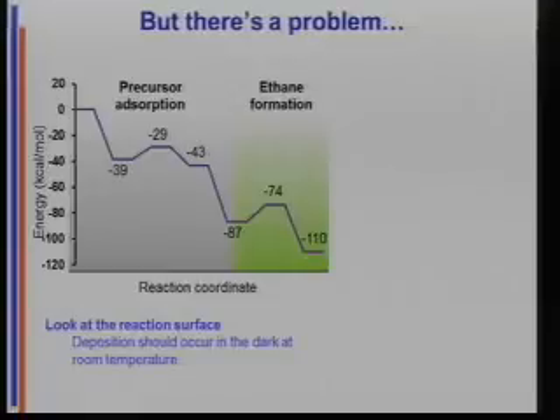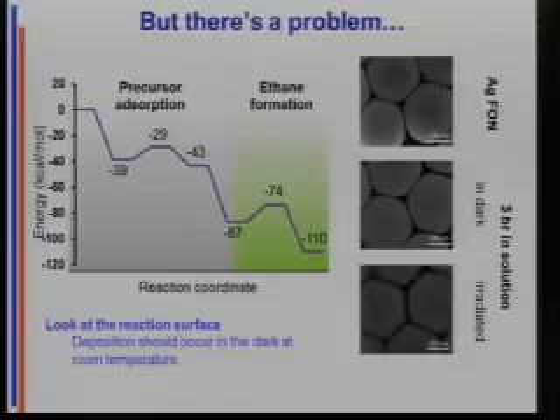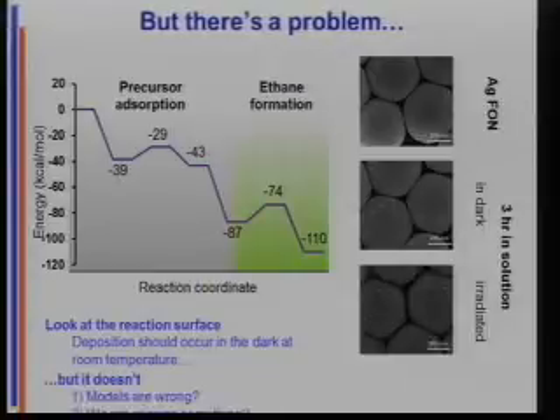And then you do the control experiments. Here's the substrate. Here's the substrate held 3 hours in the dark. There's no deposition. Okay? Then here's the substrate irradiated. There's the silver nanoparticles. They're there. And so clearly that reaction surface can't be right. It just doesn't match what we see experimentally. So what did we do wrong?